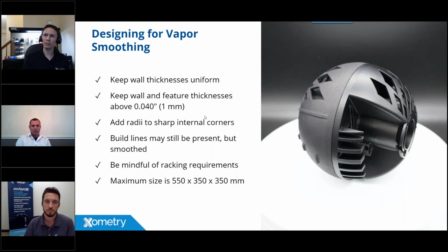Something I want to note here is that this is a smoothing process. I think some measurements I saw, the typical Ra value is going to come down to about 63 Ra, which is a measure like taking a record needle and dragging it across, and you get that up and down, and that's your variation of Ra. But if you look at these parts here, they're not being polished, and if I do have more coarse layer features on this, they're going to be present but heavily mitigated. It's just something to note from a managing expectations standpoint. It still looks great.